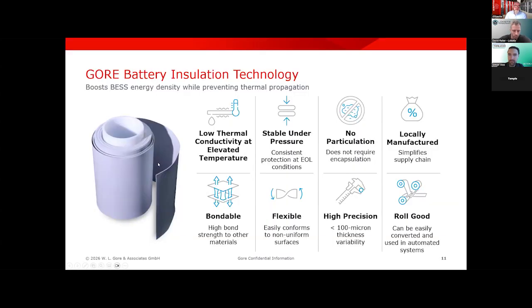So what you're having here is a thin material, 1 millimeter thick in standard, but we could also produce it in 0.5 millimeter thickness that has a low thermal conductivity at elevated temperatures, and it's stable under pressure. So it is not compressible, or the compressibility is really low, instead of other solutions what you're seeing in the market. It's not particulating, so it does not require any kind of encapsulation. It's locally manufactured in all regions, and it's bondable.